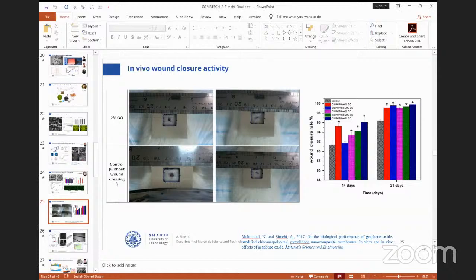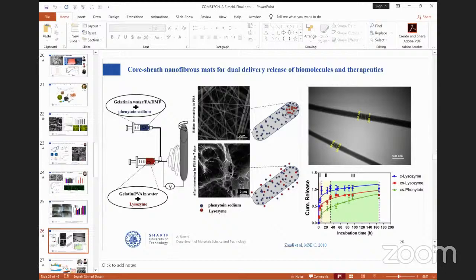In continuation of this work, we thought, okay, if we want to add some growth factors, biomolecules, drugs inside our mat, what should we do? The idea was to prepare a core-shell structure. So we used an electrospinning system with a double nozzle, and incorporated a growth factor and a drug inside and outside of the shell. So one of the materials, the lysozyme, inside as a growth factor, and the outside layer contains a drug. So we would like to have a drug and a growth factor inside our mat in order to accelerate the skin regeneration.